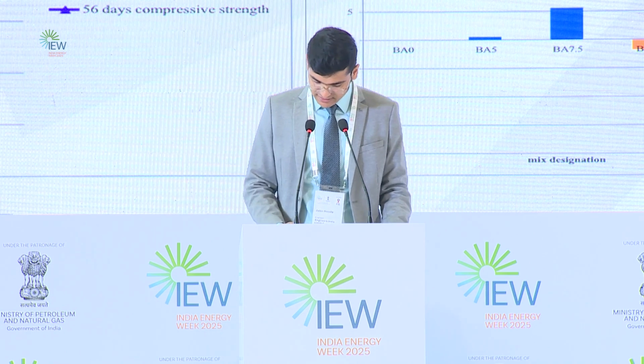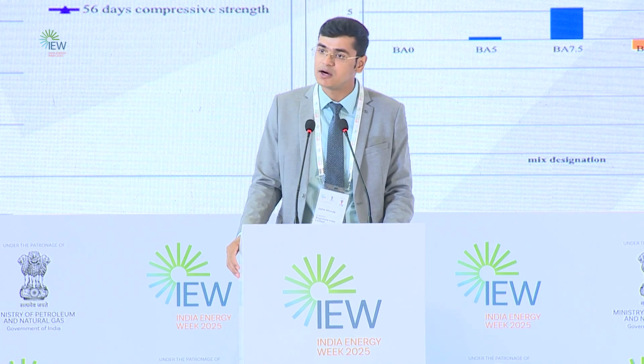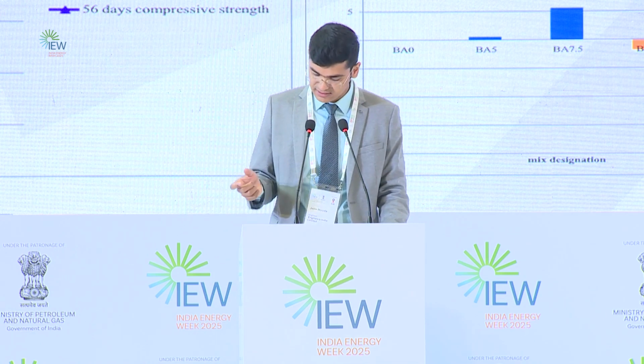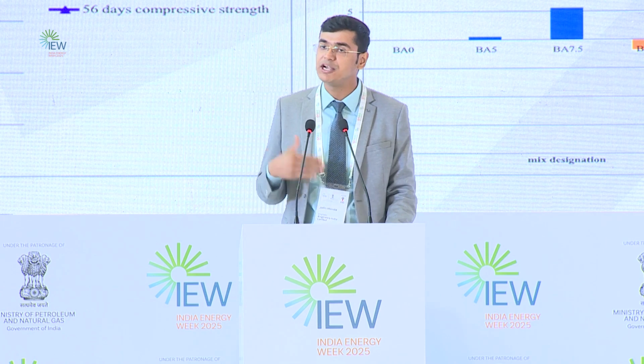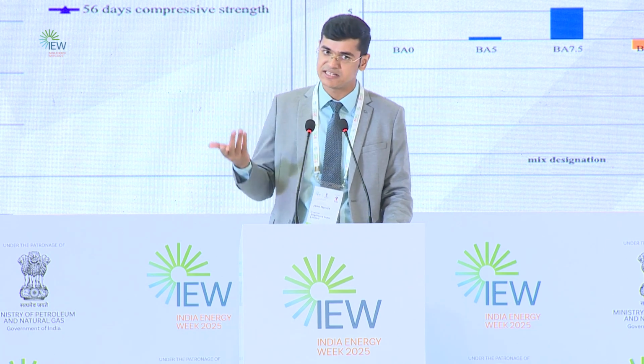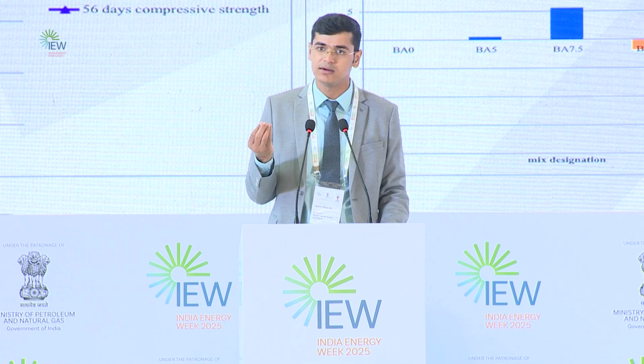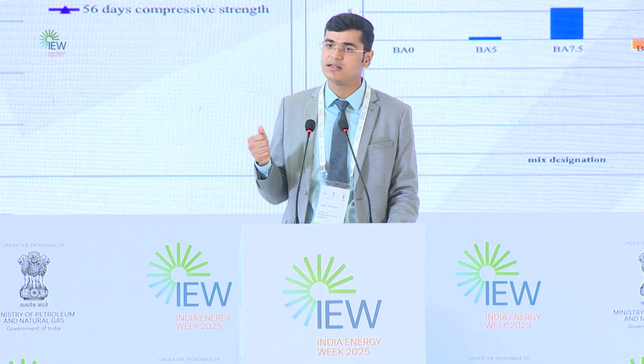Directly coming to the results, you can see the compressive strength versus SCBA percentage chart: at 7.5% we received the optimum compressive strength. It is clear that the percentage of SCBA results in an increase of compressive strength, but for SCBA specifically, the rate of increase of strength is seen at later stages. Because it is a pozzolanic material, it takes some time to react completely with water, and that's why the strength received is higher at later stages.